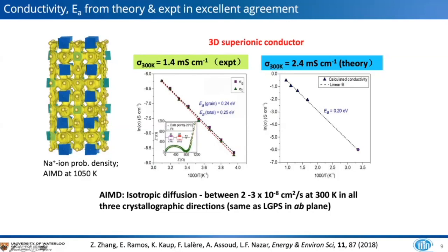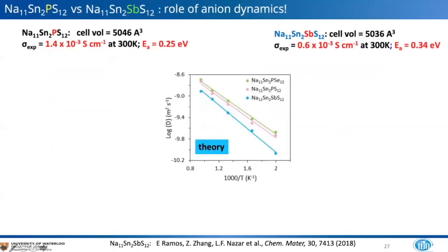So this is, as I said, a three-dimensional superionic conductor, and the diffusion coefficient that we obtain from AIMD is about 2 × 10⁻⁸ centimeters squared per second at 300 Kelvin, in all three crystallographic directions. And that makes it somewhat similar, or very similar, I should say, to LGPS, but just in the LGPS in the basal plane.